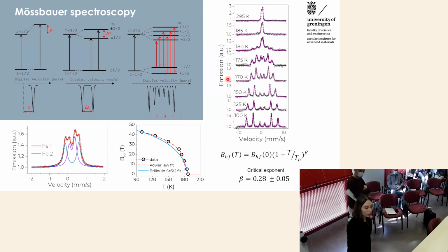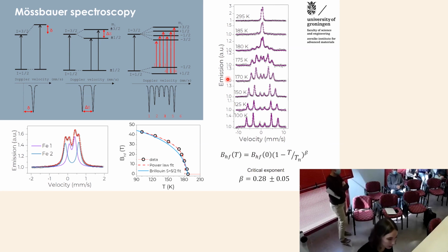I think the shape of the quadrupolar splitting depends on the shape of the octahedral environment, because the quadrupolar splitting is linked to asymmetries in the electric field environment of the iron. So if the iron is in an octahedral environment which is distorted and not perfectly symmetric, that gives rise to the splitting. And I think that the difference in the amplitude is related to the asymmetry in the octahedral environment of the iron atom in the structure.